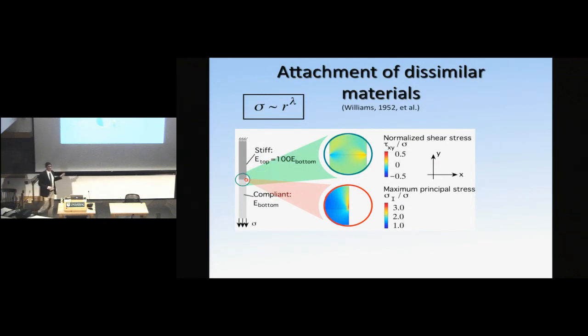And many of you know this, of course. When you attach 2 dissimilar materials together, the challenge that you have to overcome is a stress concentration. And in the case of linear elasticity, it's actually a stress singularity that can occur under certain conditions at the attachment between these 2 different materials. So we're plotting shear and principal stresses. And in a very localized region, right around the edge of a free boundary, the stress can shoot up to infinity. So in an engineering structure made of metals, that's not always so big of a problem, because metals undergo plasticity, nonlinearity, in which the material becomes more compliant if it has excessive strains. And that directs the peak stresses away from the point of highest stress concentration.